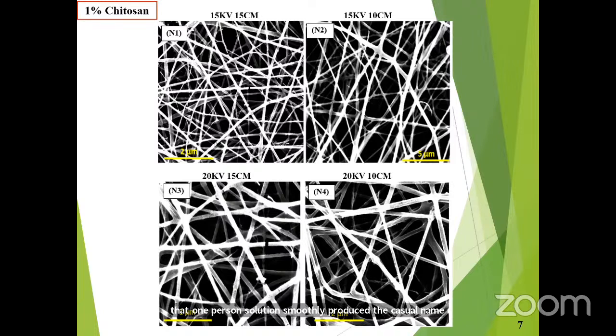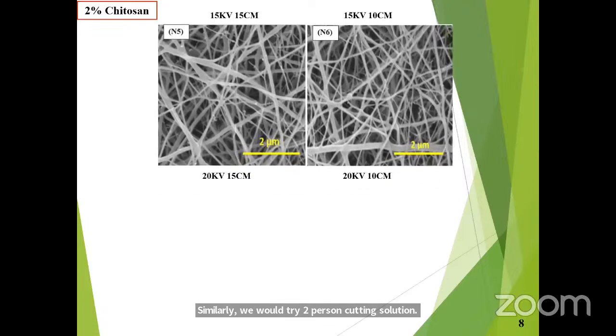So we proceeded with the experiment by increasing the concentration of chitosan to check the impact of higher concentration on nanofiber production. In our next slide, similarly, we tried 2% chitosan solution concentration, which also showed smooth nanofiber production without beads.